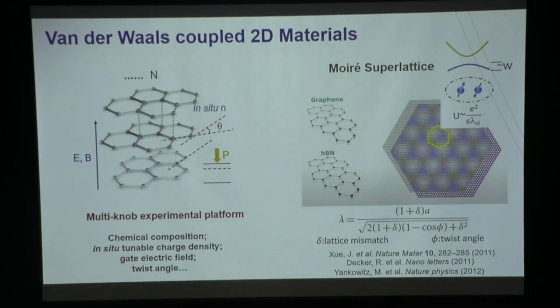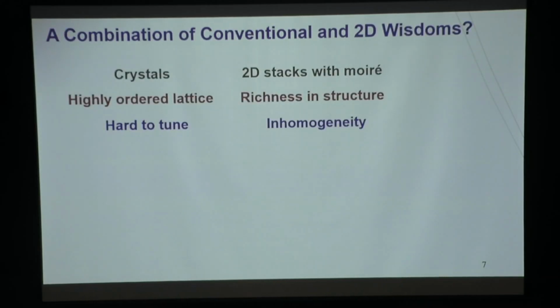Of course, you can also play with the twisting angle between the layers to further control that periodicity. What you get eventually is that you can further control the band structure and the interaction energy scale when you put the electrons into such an additional periodic structure that's much bigger than the atomic lattice. So I was enlightened by both of these 2 types of wisdoms. The first wisdom is chemistry is great. It gives us highly ordered structures, very robust, highly repeatable. However, it is hard to tune. Once you grow the crystal, you can hardly tune its properties through something called gate voltage.